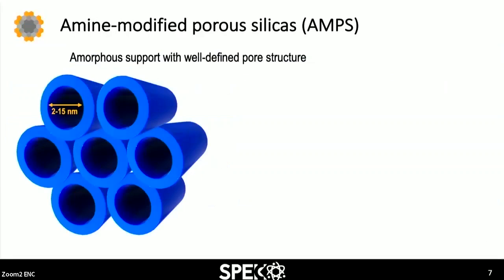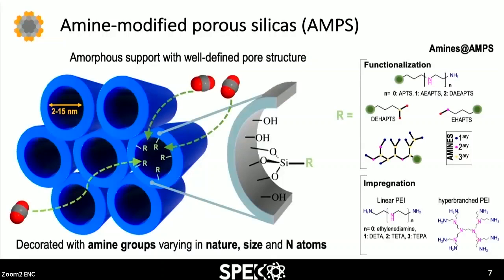And why? First of all, they have pores that are wide enough for the application that we want, and also they are highly tunable, which means that you can tailor their chemistry, tailor the number, the nature, and the size of the nitrogen atoms that you insert into your material. So you can see here that you can change not only the nature and the size of your amines, but also the way you insert those amines into the material.